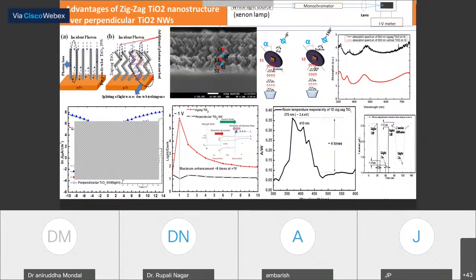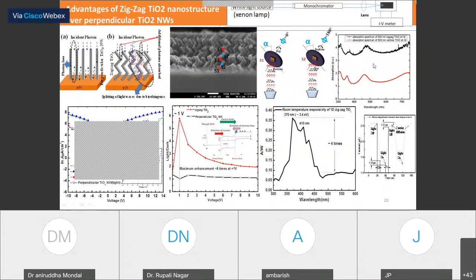We have used these two kinds of materials for optical absorption. We have seen the optical absorption for the zigzag structure is more. The idea was that the incident photons which would be lost due to absorption or reflection from the silicon wafer directly will be absorbed into the active medium without losing any photon. Indeed, this idea worked out, and the absorption of photons inside this zigzag structure has been enhanced. We have also seen the responsivity of the zigzag nanowire-based photodetector has been more as compared to the normal nanowire-based photodetector.